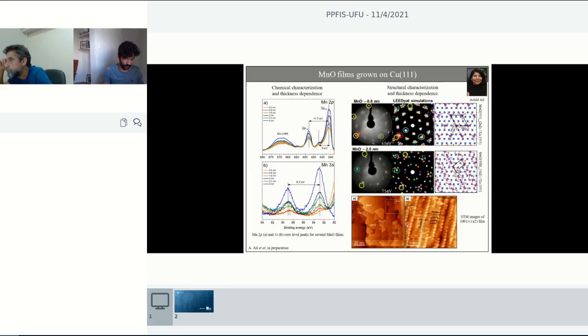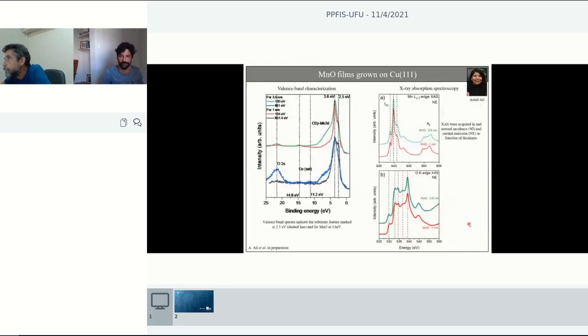And then this is important because on copper, you have a lot of catalytic properties that can bring to the system the combination of manganese oxide and copper oxide. And at the same time, we have actually a nanomaterial that has very unique properties, although it's MnO, because it's a MnO(001) with this 1/2 superstructure on the surface, we have a lot of low coordinated atoms that are expected to play a role in the reactivity, especially for CO2 oxidation, for CO oxidation.